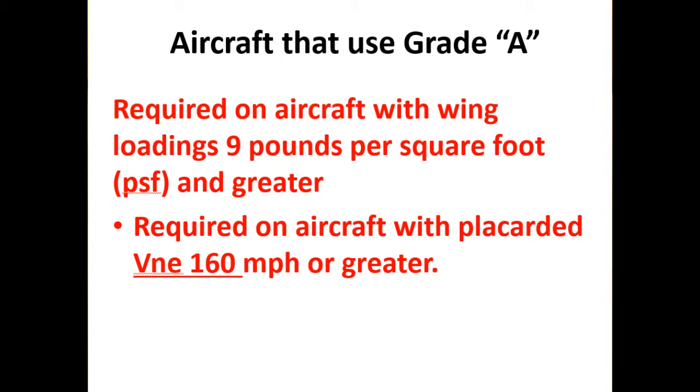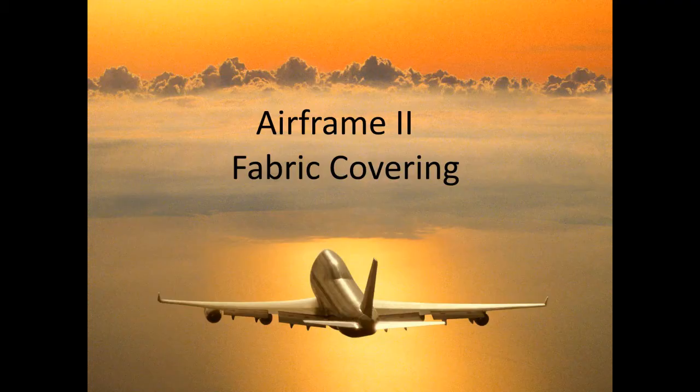The type of fabric covering required for an aircraft depends on its wing loading and its VNE speed. The condition of fabric covering must be determined at every 100-hour and annual inspection, because the strength of the fabric is a definite factor in the airworthiness of the airplane — especially since fabric is covering our lift-creation surfaces.